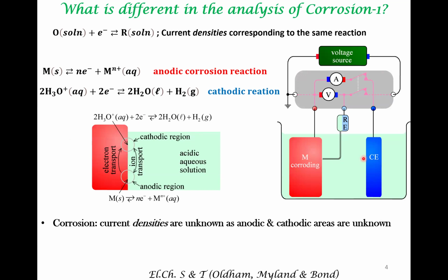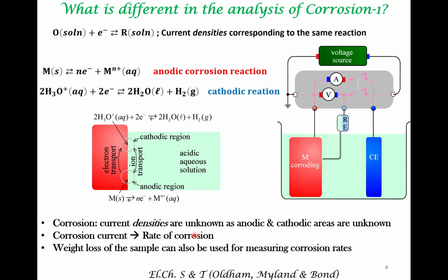In corrosion, current densities are unknown because the area relevant to the anodic part and the cathodic part is not very well defined. So we typically only deal with current as opposed to current densities. When we were quantifying the properties of this reaction, we looked at current densities. However, in corrosion, we are mostly discussing just current and not current densities because anodic and cathodic areas are unknown. From corrosion current, we can get to the rate of corrosion. It is also important to understand that there are other ways of getting to the rate of corrosion. We can look at weight loss of a sample. When a metal gets corroded and dissolves away, the weight of the sample, metal sample, decreases. So that is also a measure of corrosion rate.